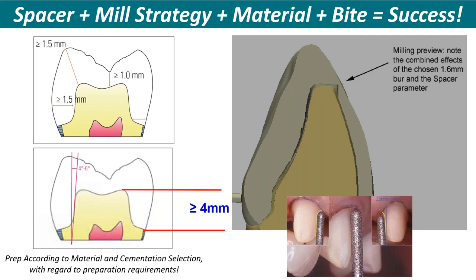But when it comes to milling, you want to be able to use the size of burrs that the milling machine can create. If the burr that you use intraorally is too narrow, you're going to have a very wide cement space after it's milled in the machines, because the burr is much larger than what you used in the preparation. So make sure that you understand the concept that the best seating restoration has a uniform material thickness and a uniform adhesive gap or cement gap. We don't want the machine to overmill and have thick areas of bonding agent or very thin ones. That's a no-no. So we prep it correctly and everything will go smoothly.